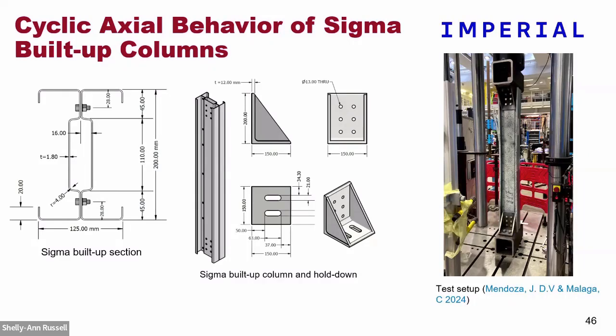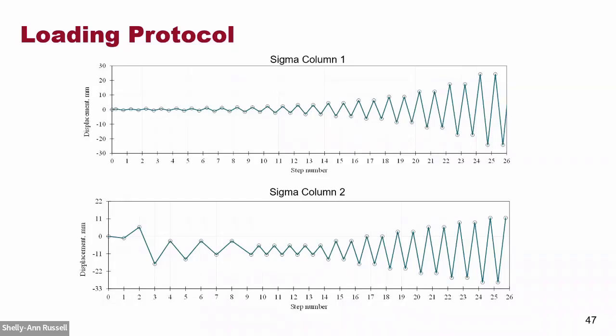We sent them these materials with these hold downs and these specimens, and they have their setup in their laboratory, as you can see here. For the first test, they used the same FEMA loading protocol for sigma column 1. But based on their first observation, there was a lot of local damage to the connections. So we changed the loading protocol to work more in compression, with a slight tension, mainly on the compression side. It's a near fault protocol, and we decided on this protocol for testing the second sigma column.